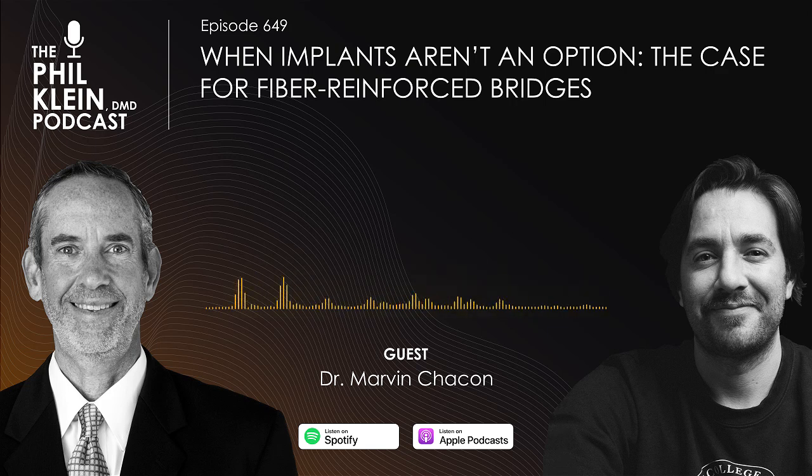And that instrument you're talking about, Dr. Marvin, I know you're getting some prototypes, and that helps curve the GrandTEC glass fiber material. Yeah, the thing is, each strand of fibers comes with almost 4,500 fibers, and these fibers will behave very well if they work together. So you as a dentist, when you manipulate them, you have to keep them as a group. You can't spread them because they will start to absorb the forces individually, and that's how failures appear. A key point is to try to keep them in a group.